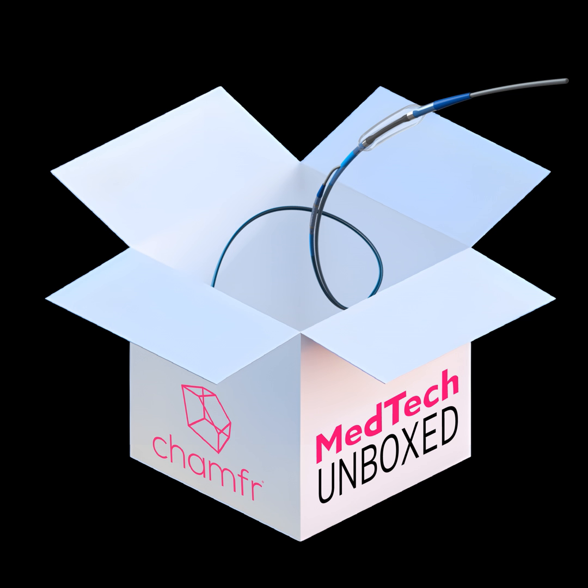So shrinkage, of course. Molten plastic comes in, and it's in this kind of semi-liquid state. As it cools, it's going to shrink and its density will increase. That's normal of any plastic and kind of intuitive if you think about really anything we work with day to day. We have to accommodate for that when we cut a tool, because we're chasing a tolerance in the finished frozen solidified plastic part, maybe plus or minus thousandths, plus or minus 25 micron, sometimes tighter.